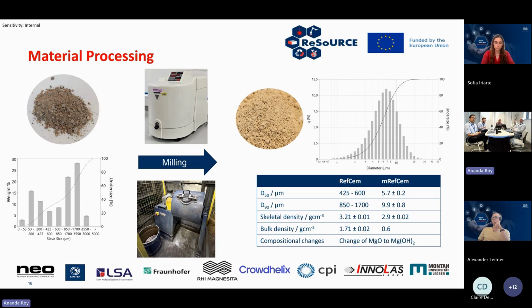But due to how we process these materials, so we do a wet milling process, we see some change of the materials from magnesium oxide to magnesium hydroxide. We get some slight changes in the properties in the materials with this change. So a slight reduction in the skeletal density. But actually, magnesium hydroxide is potentially quite an interesting material for fire retardant properties.